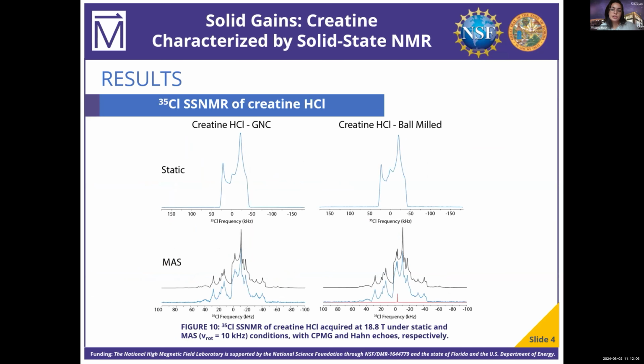Since this is a hydrochloride salt, we can also probe the solid forms using chlorine-35 solid-state NMR. These spectra are really complicated, but really useful for the structural determination and also reveal some presence of sodium chloride indicated near the small peak by the negative 41 parts per million region.